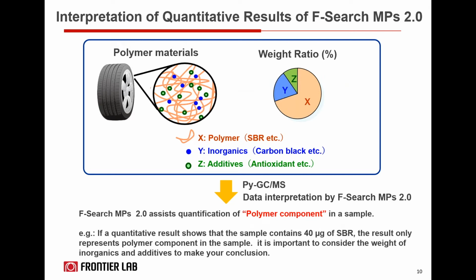So step 4, which is the last step as I just mentioned, is the interpretation of your quantitative result, or actually qualitative result, of your F-Search. After running your samples and your standards, you would use your F-Search MP 2.0, specifically for microplastic analysis in this case, to perform both quantitative and qualitative analysis of polymeric components of your sample.